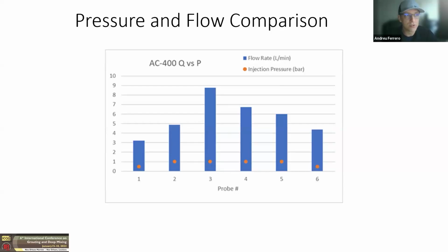The AC400, which is the low viscosity acrylate, around 3 to 6 centipoise, did not see a change in flow rate with the injection pressure changes. Actually, we couldn't get a pressure reading on the pressure gauge because the material that we were injecting was so low viscosity. It was just flowing through that silty sand and not back pressuring up. So we were able to increase that flow rate, but we didn't see any changes in the pressure.